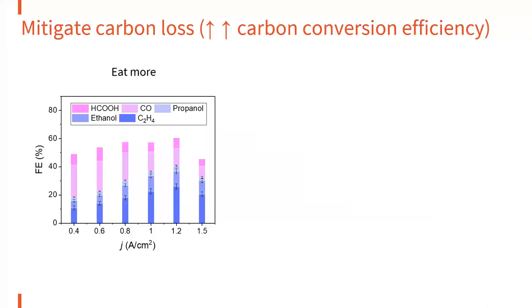So actually, our outer goal for doing this acidic CO2 reaction is to mitigate carbon loss, because we know that carbon loss is a huge problem. To mitigate carbon loss means to improve the carbon conversion efficiency. So how can we achieve our goal? The first thing is that we can feed more CO2. That means we operate the reaction under higher current density, so that we have two benefits. One, we improve the production rate. Two, we create a higher local pH so that we can promote the C2 product selectivity.